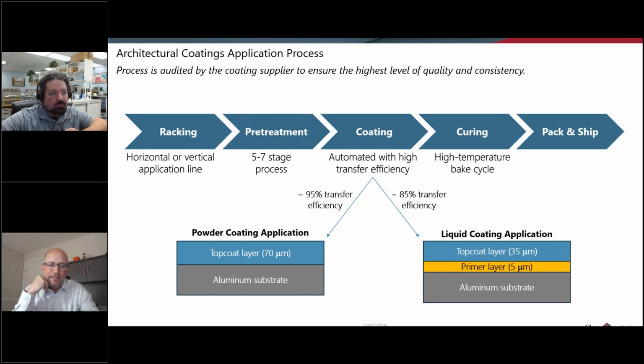On the powder side of things, about 95% transfer efficiency is usually the number that's quoted. The reason that one is higher is because it's also electrostatically applied, so most of the material is going to hit the part and stick to the part and be able to be used. But what goes past the part can also be reclaimed and recycled. So the application process is set up so that material is captured and recycled through and continues to be used as long as you're spraying the same chemistry and the same color for long periods of time.